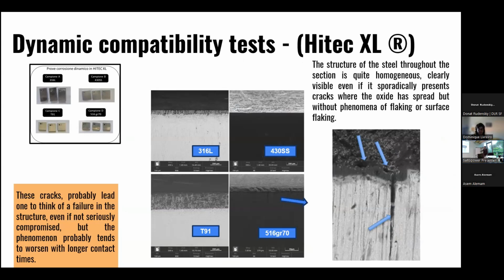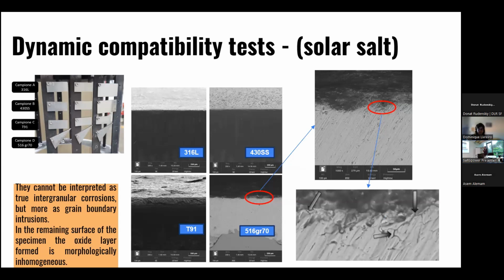That is this picture. I zoomed in on the layer between the oxide layer and the steel. And if the structure of the steel is quite homogeneous, there are visible some cracks where the oxide has spread, but without phenomena of surface flaking. But it is not so good for a steel, something like this, because the salt can go inside and crack the steels. The same thing regarding the solar salt test, of course, at higher temperature.